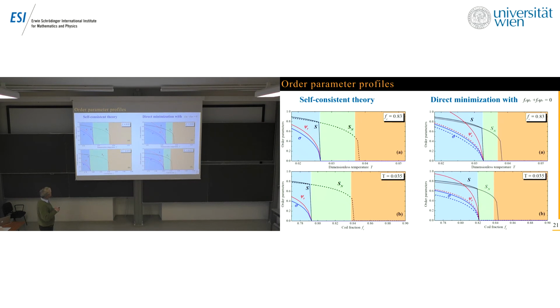No, here, for example, everything is consistent. So here all order parameters behave nicely, and it can be shown that they approach 1 only at infinitely low temperatures. I just presented this for illustration, because even in the original paper of Leibler, he has introduced just this condition formally. And this may look okay, but if you go away from the spinodal, then order parameters will shoot up and will exceed 1, which is not visible in Landau-de Gennes, because nobody takes seriously the values of order parameters which are obtained in Landau-de Gennes theory.